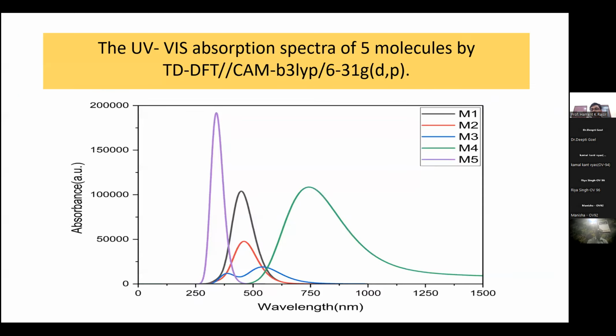I have also presented here the UV-vis absorption for these molecules. If we look at the UV-vis spectra over here, ideally the HTM should absorb within the 400 nanometer range. So till 500 is also fine. Why? Because 550 to 900 nanometer is what the perovskite, the main layer, absorbs. So we don't want hindrance with that particular layer. We can see that for M5, the absorbance is high, as well as the range is fine. For M1, it's fine as well. For M2, the absorption is a little bit low, but it is lying in the right area where we want it to be.